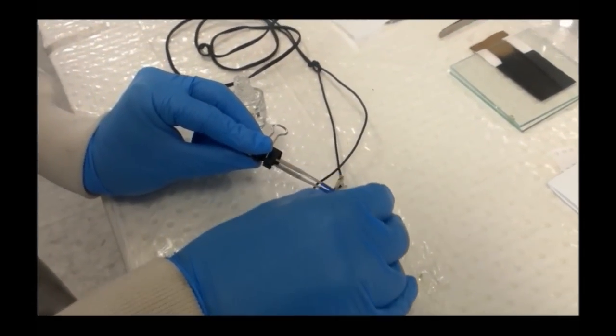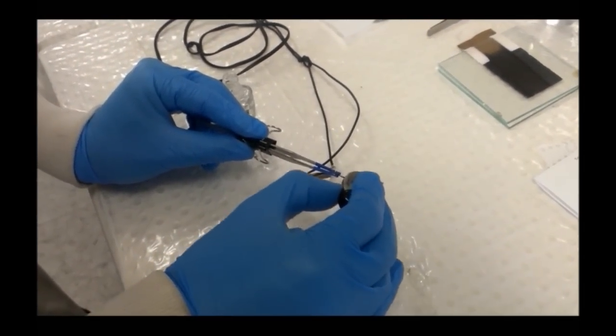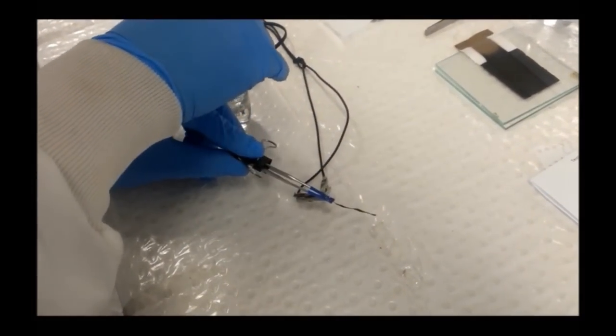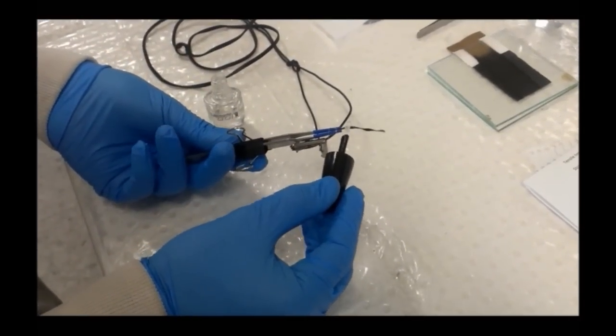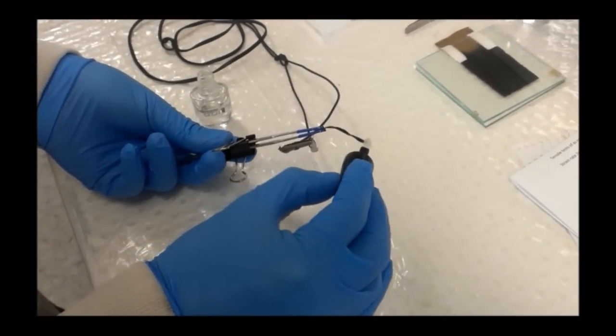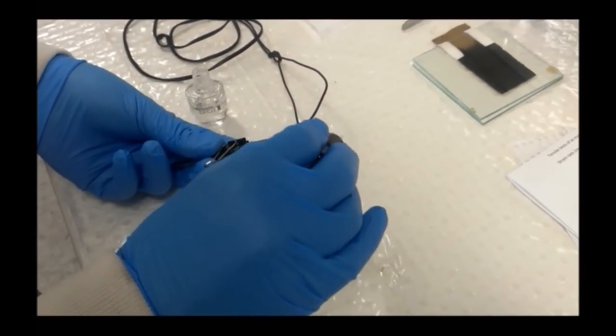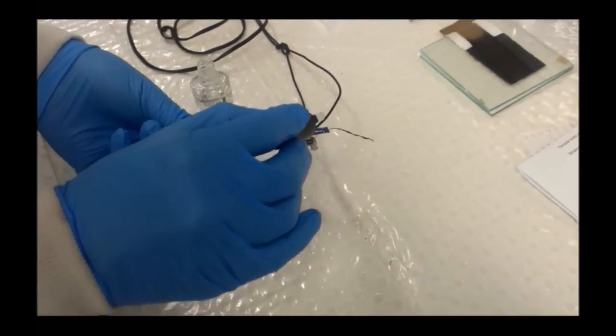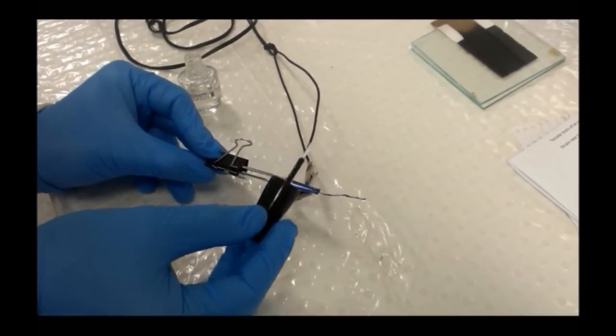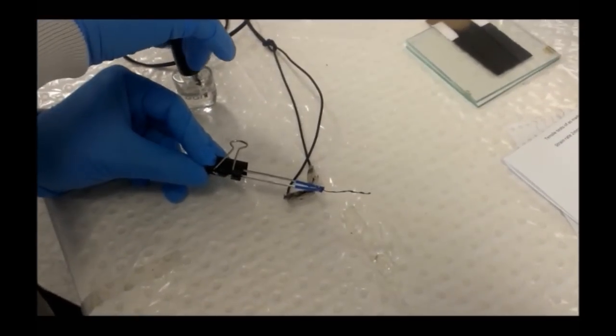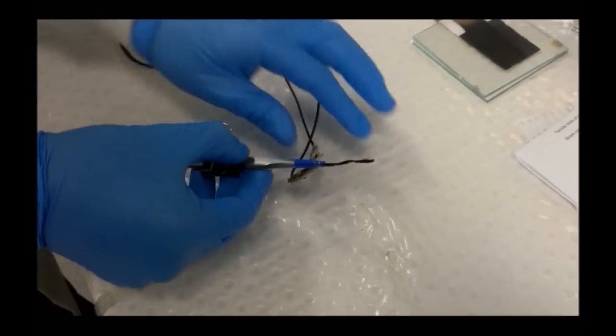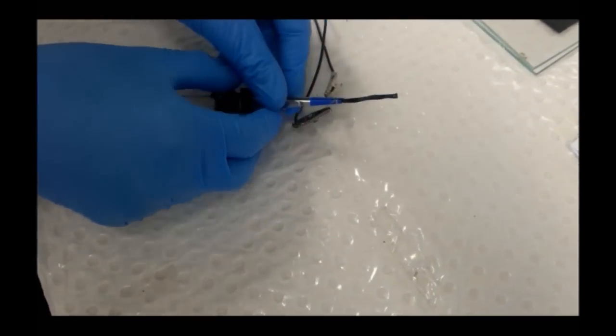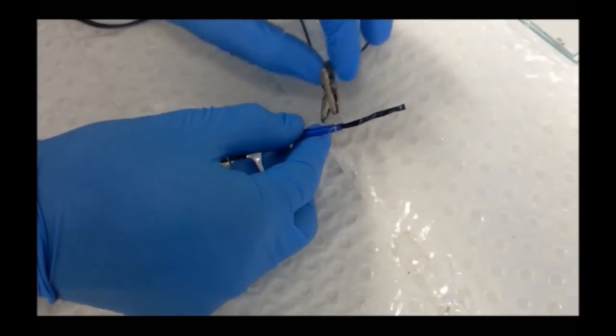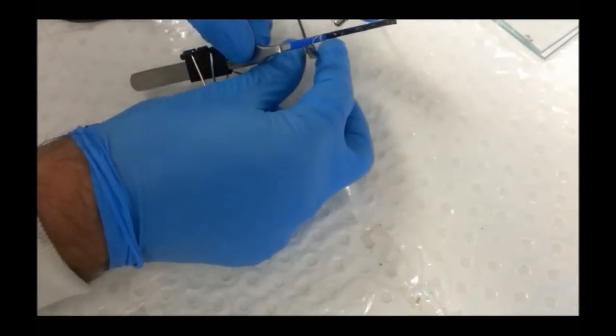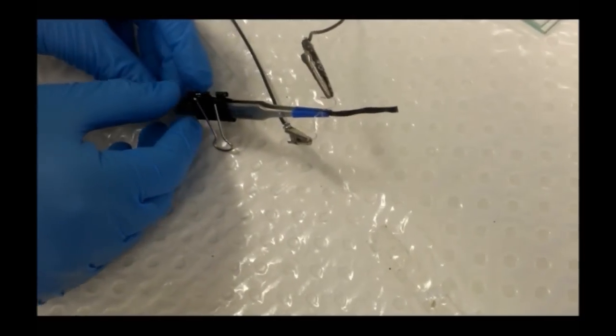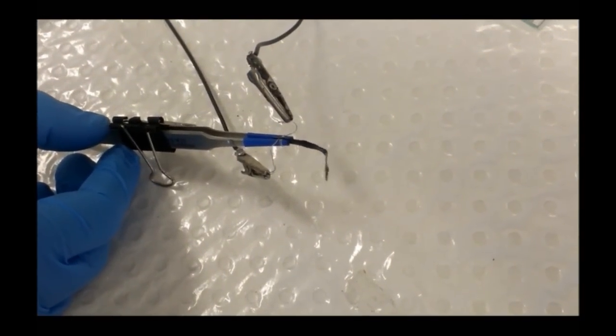trying to get a fairly thin coating. Remember to coat the edges as well. And this extends the lifetime of the actuator once it's actually immersed in water. Now for best performance, it would also be best to coat the electrode areas, but I don't want to do that in this case because I want to reuse this tweezer setup. But for a more permanent, longer lasting connection, we would coat everything, try and encapsulate everything. Okay, so I'll just make sure there's no shorting out. Let's see whether it still works. Yep.